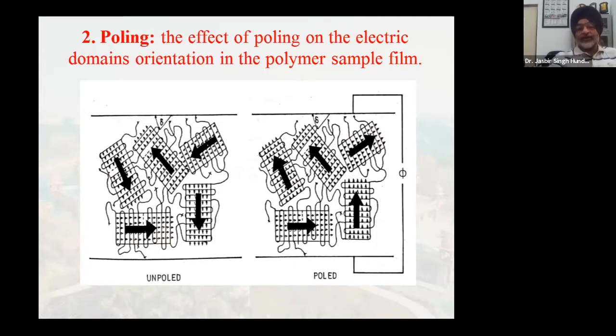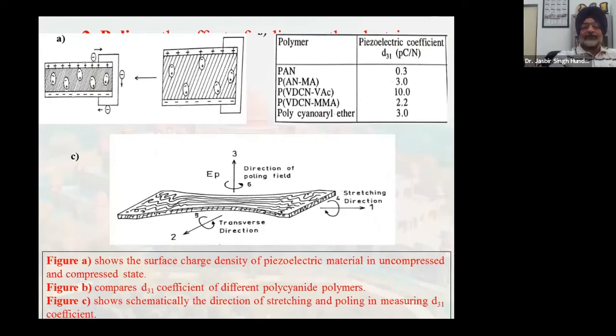So domain orientation gets better along the field direction due to poling, right? Now say in the first case, if you look at figure A, that is a piezoelectric film, and it has a lot of dipoles within. Now these dipoles are near the surface, so we have some mirror charges developing on the surface. Since the positive ends of the dipole moment are on this side, we have negative charges on the surface. These are again mirror charges.